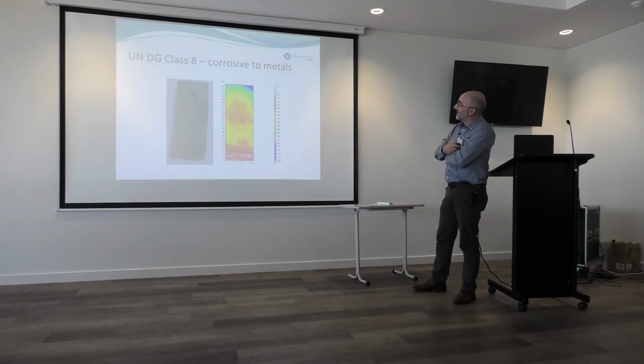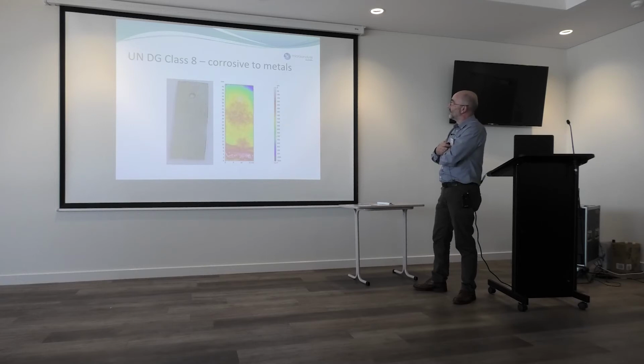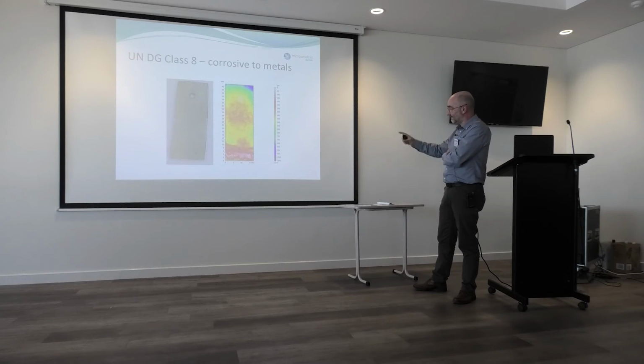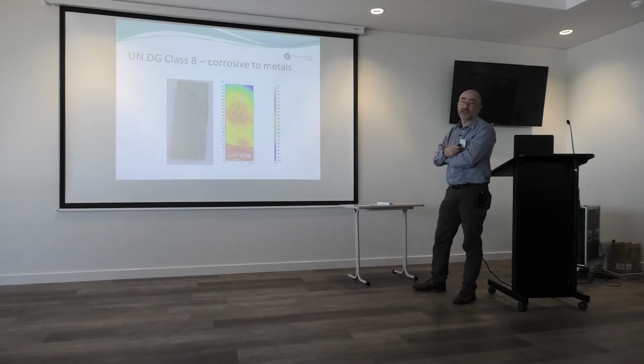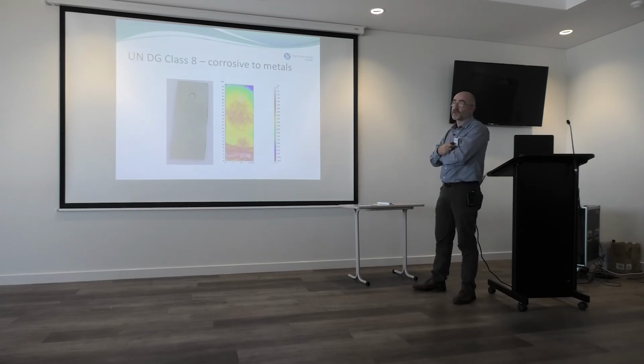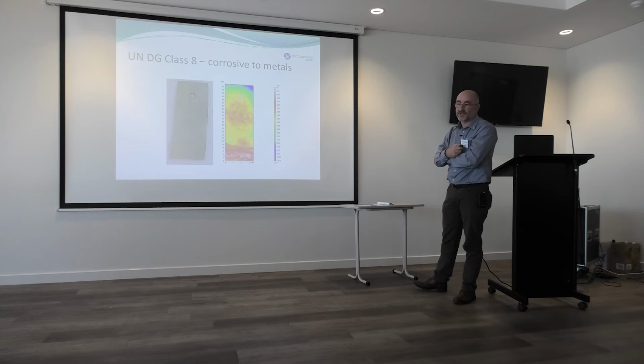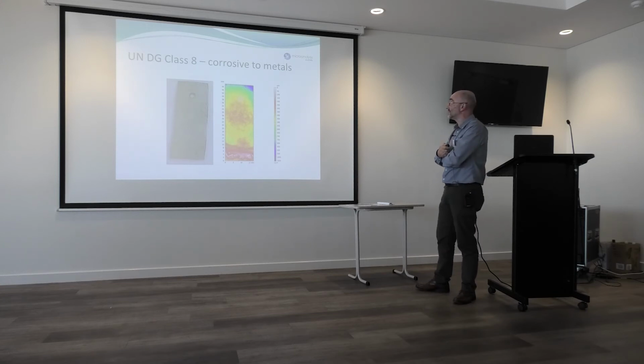So there's a coupon image with the Solaris scan giving you the depth of corrosion, the surface loss, over that entire area. The classification for the UNDG was 120 microns, so if there were any pits greater than 120 microns or more than a certain amount of mass loss, it was deemed to have failed, and the certificate went back to the shipper to say that the material was not safe to be shipped in that condition, and they had to do something about it.